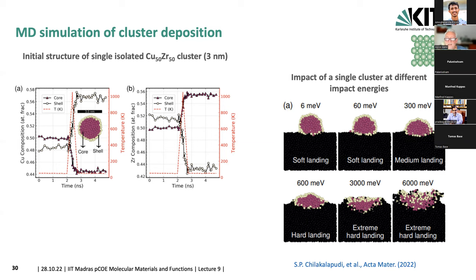And what he did first, he looked at the structure, the atomic distribution of the atoms in such a small cluster, which is 3 nanometer in size here. And what you see is that there is an enrichment of copper at the surface of the particle. So it's not a homogeneous particle in terms of composition. There's always some segregation to the surface. We have to keep this in mind because later the surface becomes what interacts with the next particle. So you have the formation of the interface over there.